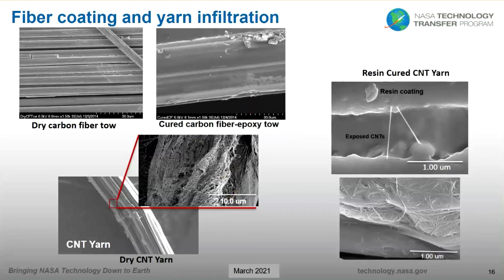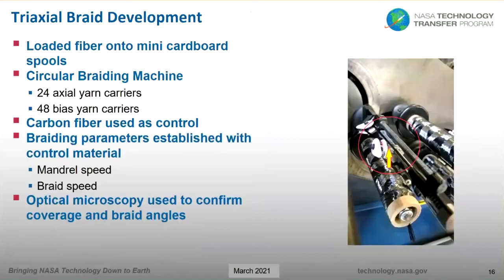So since the mechanical properties were improved with the introduction of the carbon nanotube yarns, the optimal carbon nanotube yarn concentration was determined with the carbon fiber material that we used. And so we felt that it was safe to proceed with braiding. First, I found a way to make a master batch of a continuous tow of the hybrid, and then those fibers were loaded onto mini cardboard spools like what I show here. And these are the spools that are used on the braider.